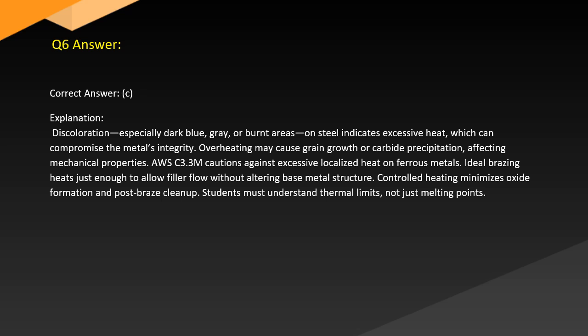Answer. Correct answer: C. Explanation: Discoloration, especially dark blue, grey, or burnt areas on steel, indicates excessive heat which can compromise the metal's integrity. Overheating may cause grain growth or carbide precipitation affecting mechanical properties. AWS C3.3M cautions against excessive localized heat on ferrous metals.